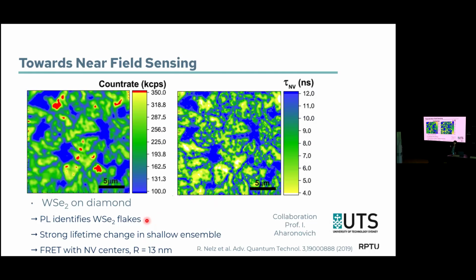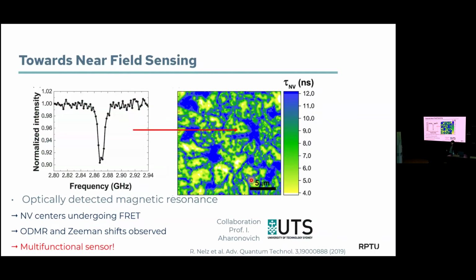And now we ask ourselves the question I mentioned in the beginning. When we are going to NV centers that are undergoing this thread, do they still function as a magnetic sensor? I mean, you're strongly changing the transition rates here, obviously. And indeed, we were able to show that if we go to these NV centers with this strong change in lifetime, we still see the ODMR, we see the reaction to the magnetic field. So indeed, the two processes can be running in parallel. So you can use the NV center as a sensor for dipoles in the vicinity and also for the magnetic field at the same time, the same NV center.